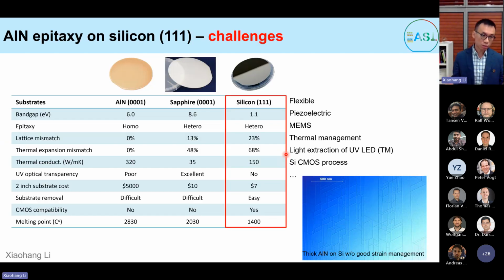So let's talk about the aluminum nitride heteroepitaxy on silicon 111 first. As you know, for growing aluminum nitride, you have a few options in terms of substrate selection. You can take aluminum nitride. It is ideal in terms of lattice mismatch, thermal conductivity, thermal mismatch, right? But it is very, very expensive, and there is no commercial device today utilizing the aluminum nitride substrate, right?